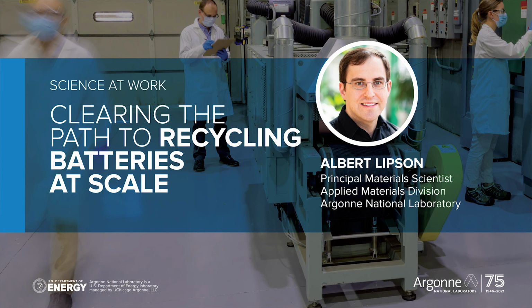After the shreds are rinsed, the next step we need to do is go ahead and remove the plastic separator. We're currently doing this by a very simple process that uses airflow that passes over the material as it's falling through a tube. This drags out the separator, and then we're able to collect it separately from the rest of the stream. And then at this point, you basically have shredded material with electrodes intact.